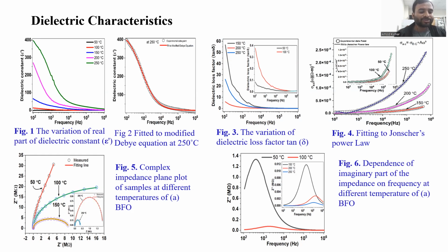The observed peak is due to the defect charge carriers. If this peak is at the lower frequency, then it is due to the grain boundary, and when this peak is at the higher frequency, then it is due to the grain.